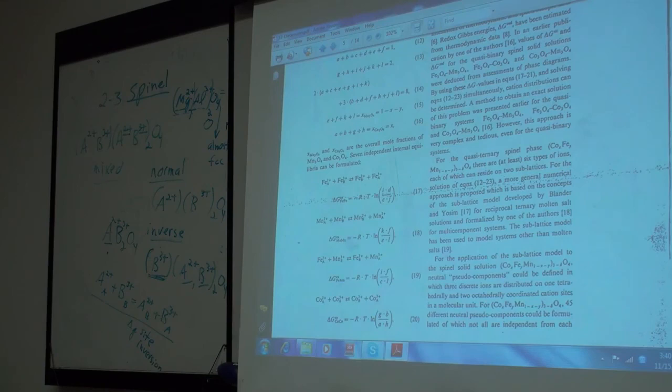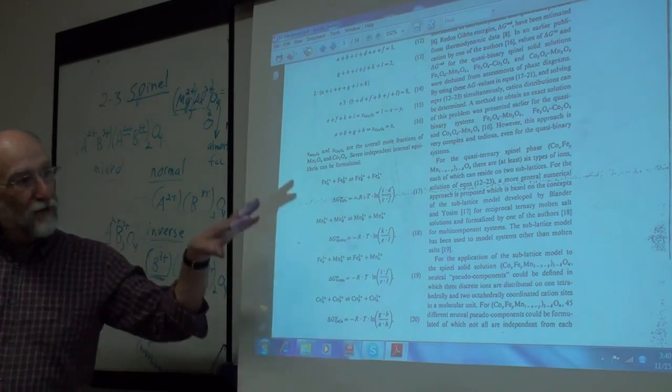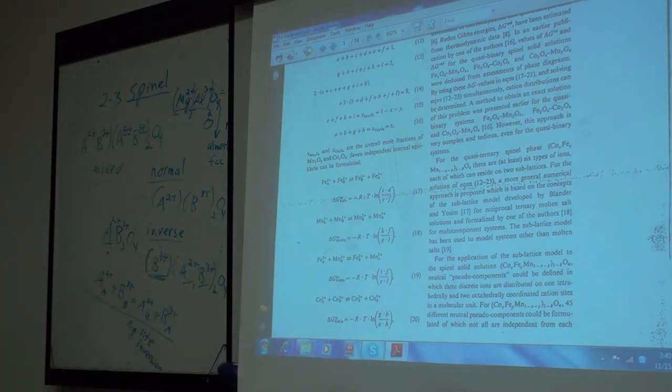The important thing, which is not easy, when I get to that, is to separate your formalism parameters from your model parameters. Even in the example I gave of the ilmenite a little while ago, you can see that you have to be careful as to what really are your model and your formalism parameters, and this can become more complicated with the spinels. But Sergei Degterov wrote a good paper once in which he really identified what are the model and formalism parameters. You can't just randomly set things to be zero. It's kind of equivalent to that vacancy, well the G is zero. No, it isn't. You have to think about what you're really talking about.